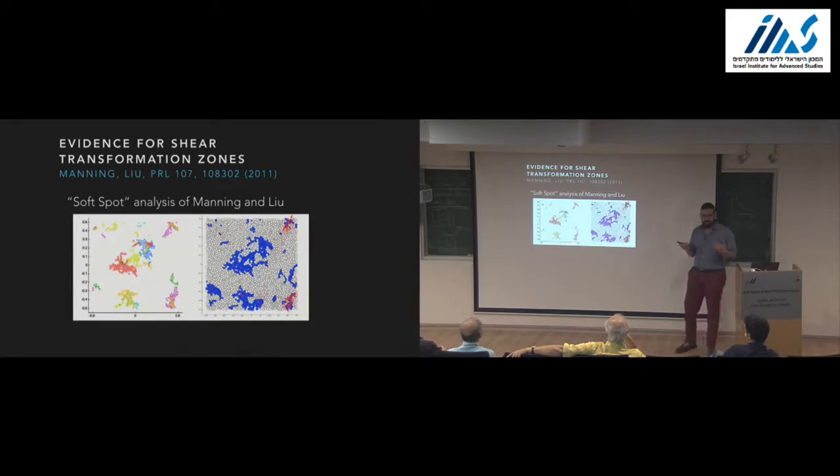The basic cartoon of the theory of plasticity that I worked on at the time was that you think about the material as riddled with these point defects that Alan was talking about. They can basically have some orientation. I've just shown two distinct orientations, but really they could be oriented anyway. If you load the material up, the bulk material up, inside the microstructure, some of these are flipping to align with the microstructure. In the process, some are getting destroyed and others are getting created and they can lead to continuous plastic flow. That was basically the picture. But the unresolved issue at that point was that we could see these shear transformation zones only a posteriori. I could look at the atoms in the original structure, deform the structure and look at how the atoms shifted, and in that way I could tell where you had a deformation event. But if you want to understand the microstructure of the material, what you want to ask yourself is, can I look at the initial structure and say you have 27 STZs in this structure and this is how they're oriented. And that we couldn't do. That was not possible. So it sort of leaves open the question, how can you do statistical mechanics on anything if you can't really count the defects or characterize them in any way?